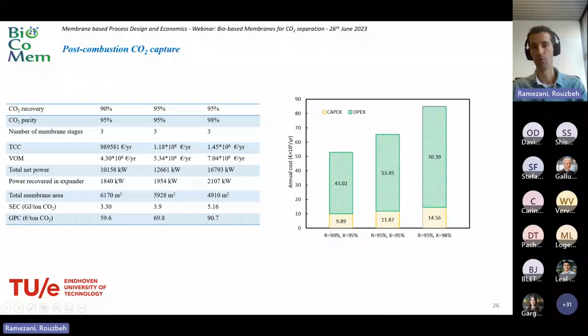And of course, I also did this for energy consumption. We also wanted to check the feasibility of the superstructure at very high gas purity and recovery. We first started with 90% recovery and 95% purity, and then checked the superstructure at different gas recovery and purity. Even at 95% recovery and 98% CO2 purity, we can use this superstructure with 3 stages to reach the separation target, but of course the cost is a bit higher, 90 compared to 59 at lower recovery.